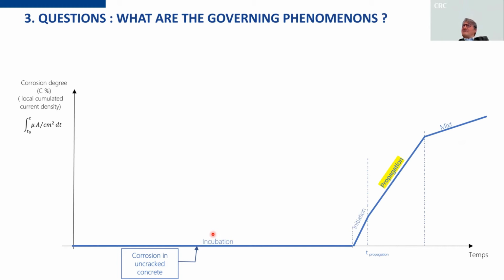To make the subject more precise, in blue, you have the standard life of uncracked concrete. During a very long period, you have an incubation period where nothing happens, the corrosion is extremely low and not measurable. Then the aggressive agent arrives and it starts the initiation, then the concrete cracks, you have propagation, and then you have spalling and mixed corrosion.